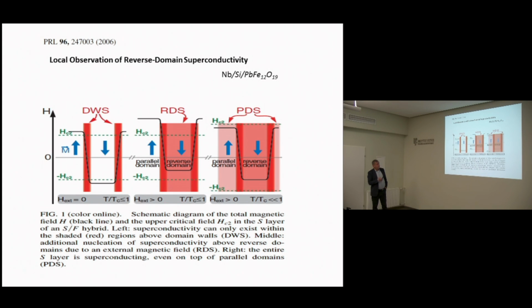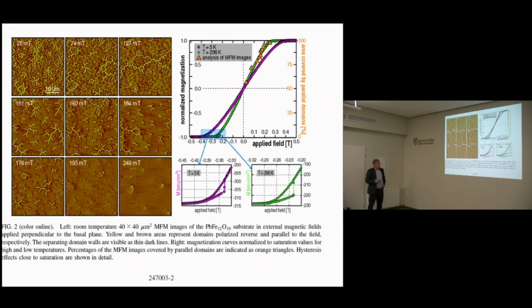The next paper, the idea of the next paper was to demonstrate, first of all, reversed domain wall superconductivity. If you go to a critical temperature much lower, then of course, if the external field is lower than the upper critical field, then we have the so-called parallel domain structure. It means that the whole area is superconducting. And again, this is the magnetic domain structure of the single crystal made by magnetic force microscope. This branched type, the yellow represents positive and the brown negative.